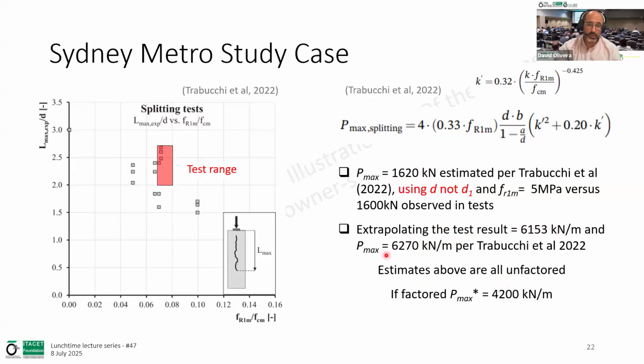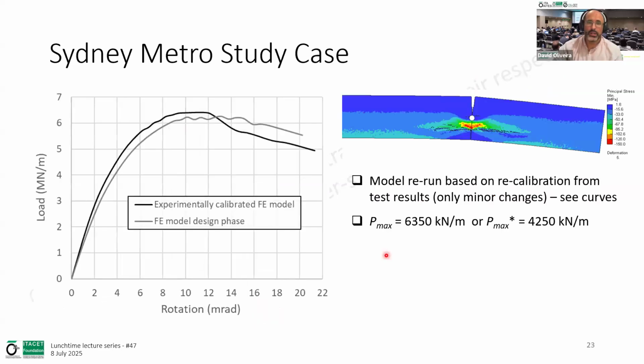And what we did is, because we recalibrated our own model, we reran the models with the recalibrated parameters, and we put here the two to compare. So our original prediction was already pretty good. The differences here were very minor. There was only a minor increase after we recalibrated. And again, the recalibration indicated that we could achieve the capacity that we needed.